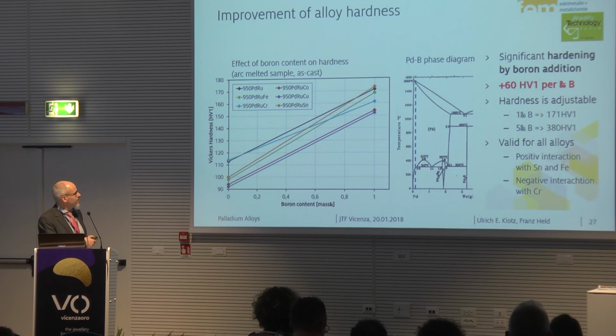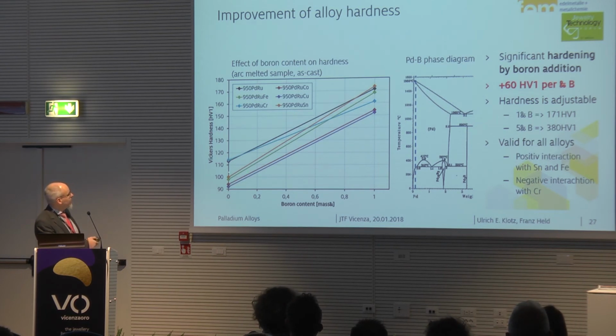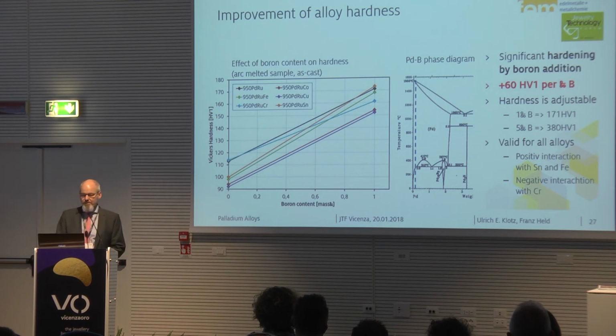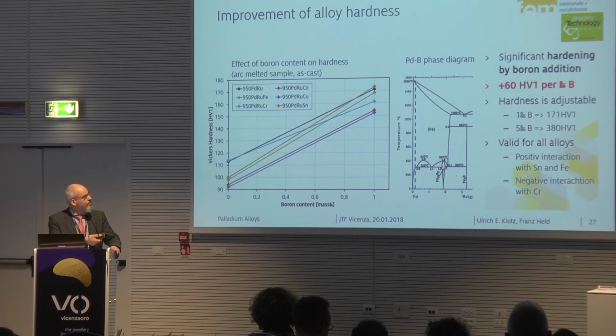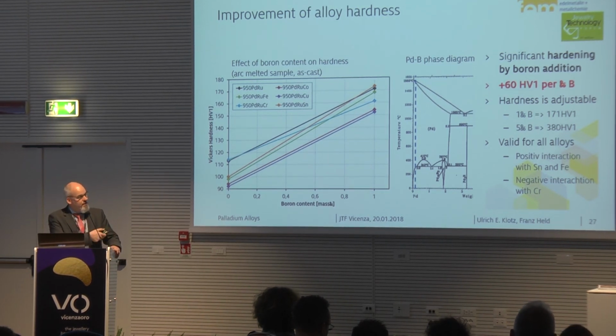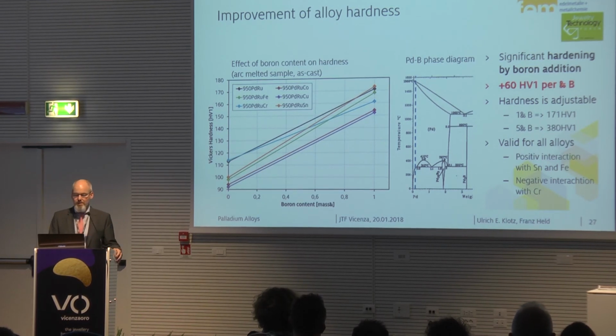This diagram shows the effect of the addition of boron to these alloys, and you see that boron has a strong hardening effect. It pushes the hardness from around 100 to around 150, 160 Vickers. Exactly the region where we want to get. In some alloys the effect is stronger, in some it's lower, but it's a general trend. So roughly we can say we gain 60 Vickers hardness points per percent of boron, and we can get to extremely high hardnesses, which of course we don't want to have.